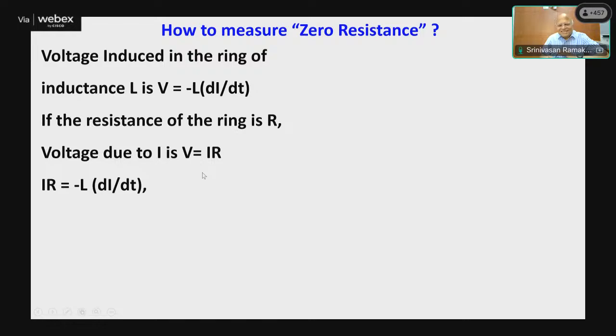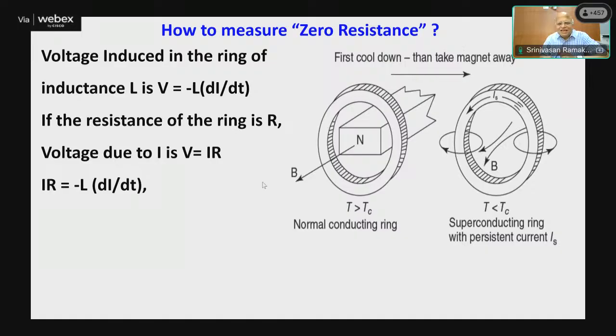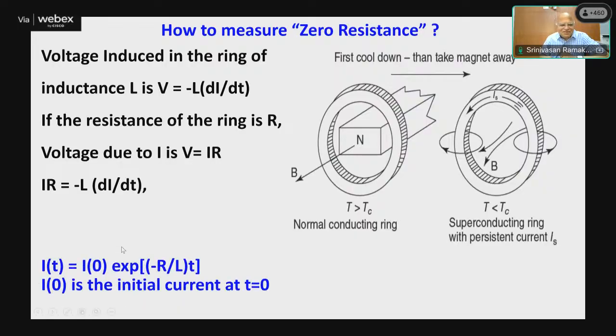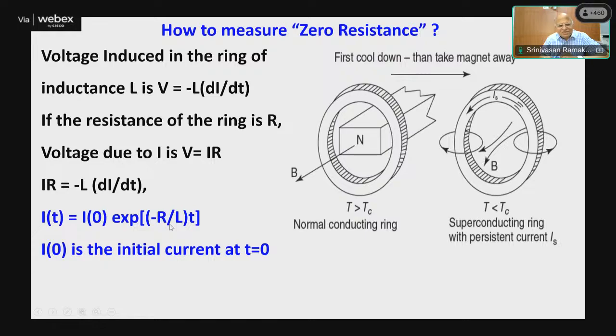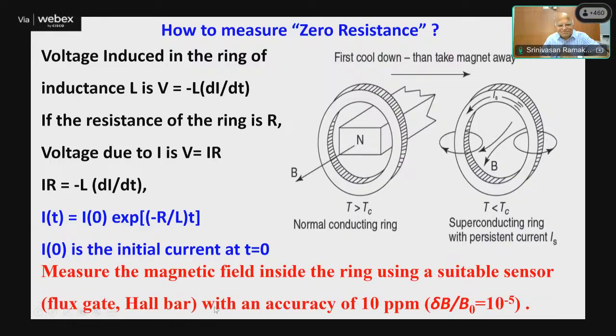Now what happens? How do you measure this resistance? You say it is zero resistance. Is it really zero? One way to do it is to take a superconducting ring, put in a magnetic field, and induce a voltage like here. Initially, the field penetrates into the ring. Then when T is less than Tc, the current will keep on flowing in the ring because there is no resistance. So one way to measure is the field inside as a function of time. It is I naught exponential of minus Rt over L, where I naught is the initial current. It is the current which you will measure by measuring its magnetic field. And then you can get an upper limit.